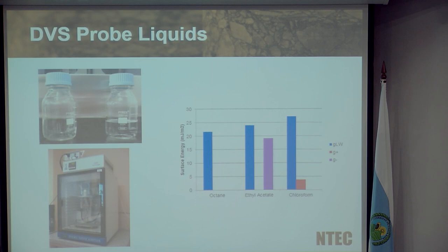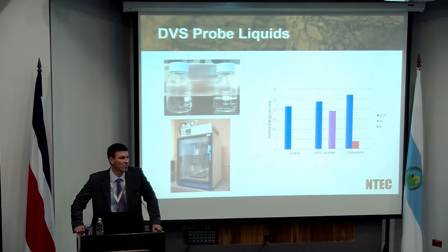There is some clever maths then, and I haven't taken that particular slide in terms of trying to explain it because it takes too long and also becomes too complicated. But if you take that relationship between the increase in mass and the partial pressure, and you work out the actual surface area of your aggregate, if you use three probe liquids, you can work out what the surface energy parameters are. So in other words, you've got three unknowns. You've got a polar component, which is divided into an acid and a base, and you've got a non-polar component. And if you take three probe gases, so in this particular example, we've got three that we've used, one of them always needs to be a pure non-polar material, which allows you to basically solve one of those unknowns. And then you end up with two other probe gases to work out your other two components, your acid component and your base component.